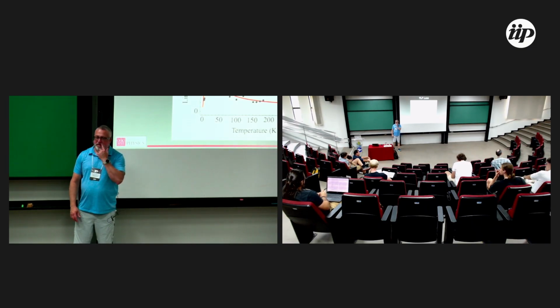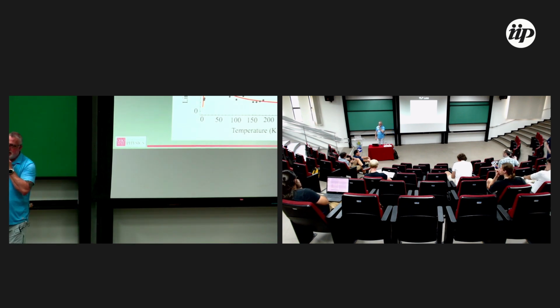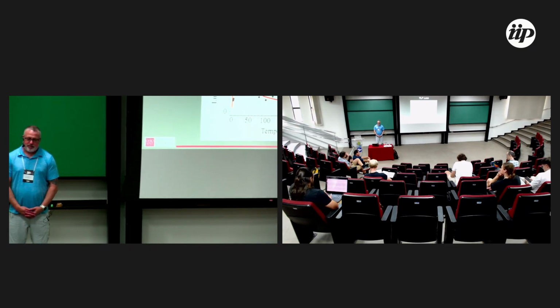Yeah, so relating to rare earths being the fluctuators that cause problems in YIG, we have maybe a situation that's quite analogous with our gadolinium vanadate as we're cooling it down, right? So at room temperature, you put your gadolinium vanadate sample in your microwave resonator, and it doesn't change the Q at all, right? It's full of spins, but because of the fast spin lattice relaxation, the line's so broad that the optical depth at the frequency you care about is kind of zero, right?